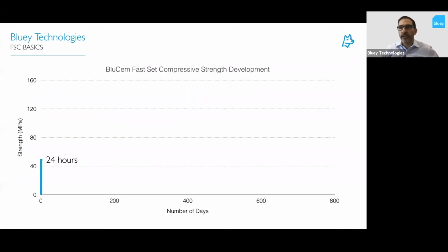So what we look at is the long-term testing, and most people are only interested in fast set cement. You know, what's happening in the first few hours? What's my strength at 2 hours? What's my strength at 3 hours? Sometimes they might ask you, what's my strength at 28 days, but not very often, because by then the item is usually put back into service and forgotten about.